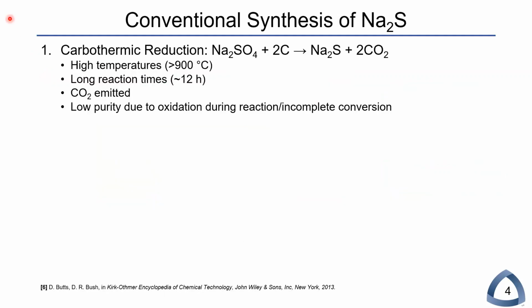The high cost and low purity of currently available sodium sulfide reflects the conventional synthesis methods, the primary one being carbothermic reduction of sodium sulfate. This reaction is conducted at high temperatures over relatively long reaction times and directly emits the greenhouse gas CO2. Material obtained from this process is typically fairly low purity due to oxidation during the reaction, as well as incomplete conversion of the sodium sulfate precursor.